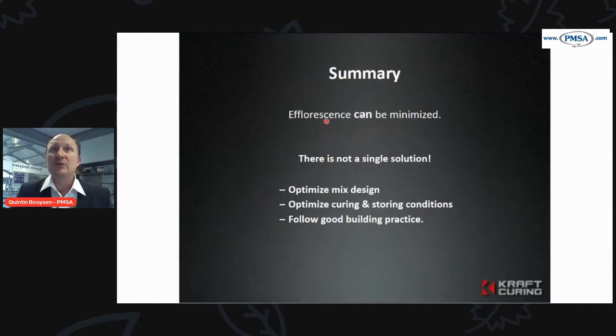Summary on the efflorescence. Efflorescence can be minimized. There's not a single solution. Optimize your mix design, optimize the curing and storing conditions, and follow good building practice. So try to minimize the water coming through capillary action with plastic sheeting, backing of plastic. So don't allow too much water to percolate through your concrete, which will bring that free calcium to the surface.